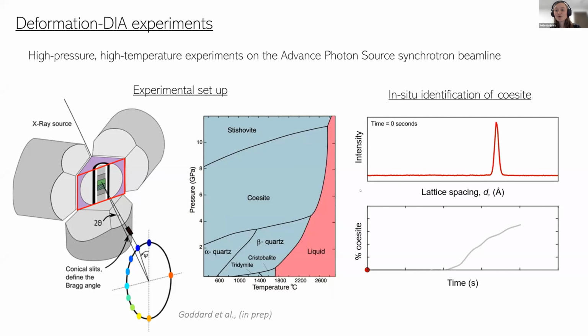So this is an example of a kind of lattice spacing of the material that we're deforming versus the intensities. At the beginning of the experiment, we just have this quartz peak, and then as you increase the pressure and you go through time, you can see that these coesite peaks are appearing and the quartz peak is disappearing. So we're able to correspond the mechanical data we have with the exact moment when we're going through the quartz to coesite field.